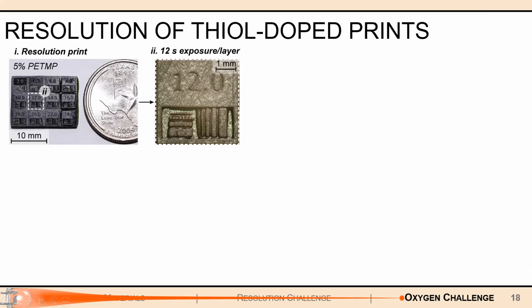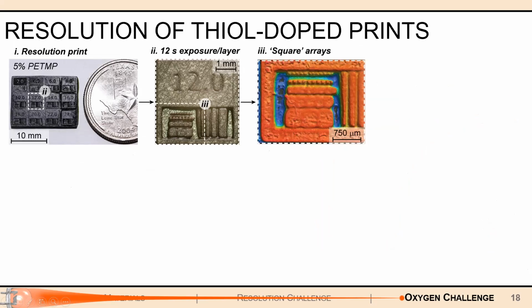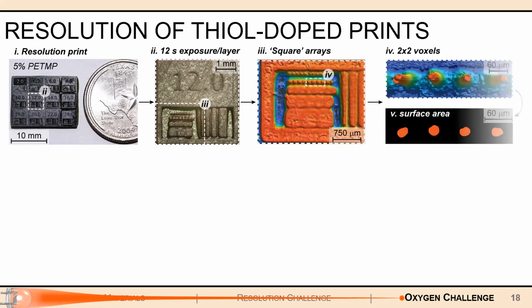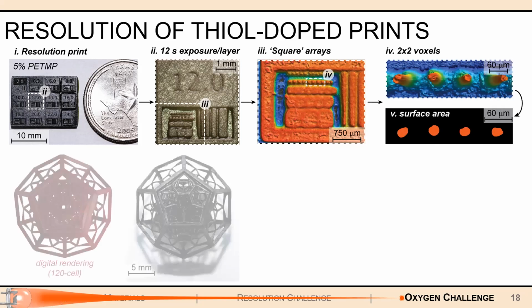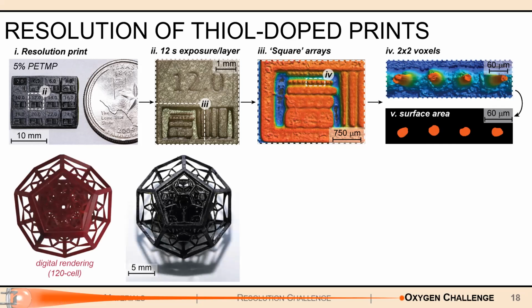And if we take a closer look at 12 seconds, we can see these nice little squared rectangular pixel arrays in the middle. And we can zoom in a little further to see basically these resolutions down at the microstructure scale. We can also, again, use these resins to print out more complex objects, like this 120-cell here. And we can see that the digital rendering and the actual print look very close, lots and lots of nice detail. We can then zoom in a little bit further.